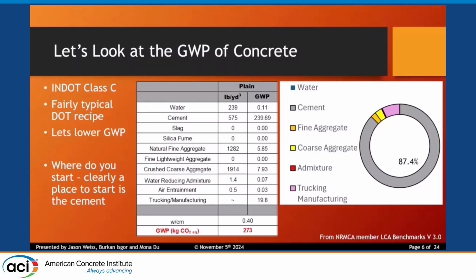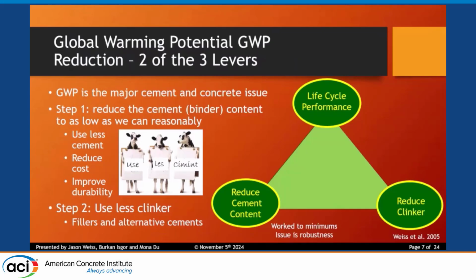If we take a typical mix that uses only cement, and I've had some people say, well, that doesn't happen in our DOT because we use other types of materials. There are some SCMs used, not nearly in the volume that they need to be used. There is a substantial amount of plain concrete that is still produced and placed. And if you look at this concrete and sum up where the global warming potential is coming from, you immediately get the conclusion that 85 to 95% of the carbon is coming from the cement. So this is why there's such a big push to reduce the cement content, reduce the clinker content, right?